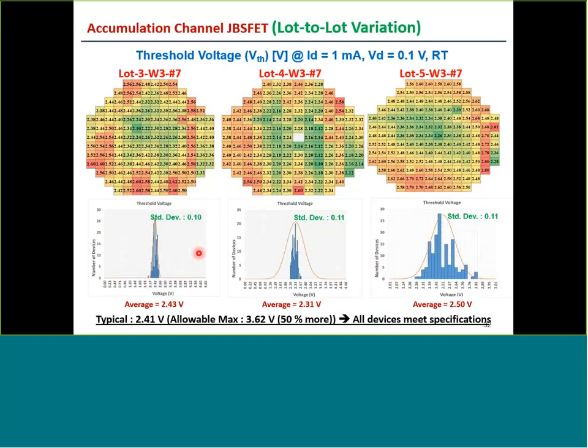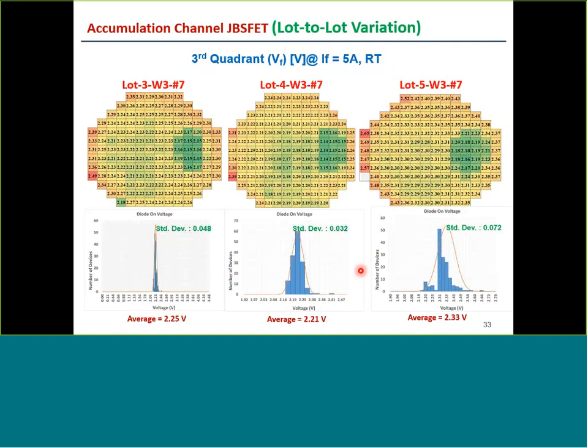The threshold voltage for these lots is running about 2.4 volts among all of them, and you can see from the chart in the lower part, the distribution is tight and the standard deviations are small. Of course, the main attribute of the JBS-FET is the third quadrant behavior. So you can see that here for 3 wafers from 3 lots, and you can see that the voltage drop in the third quadrant is in the 2 volt range and it's very tightly distributed.